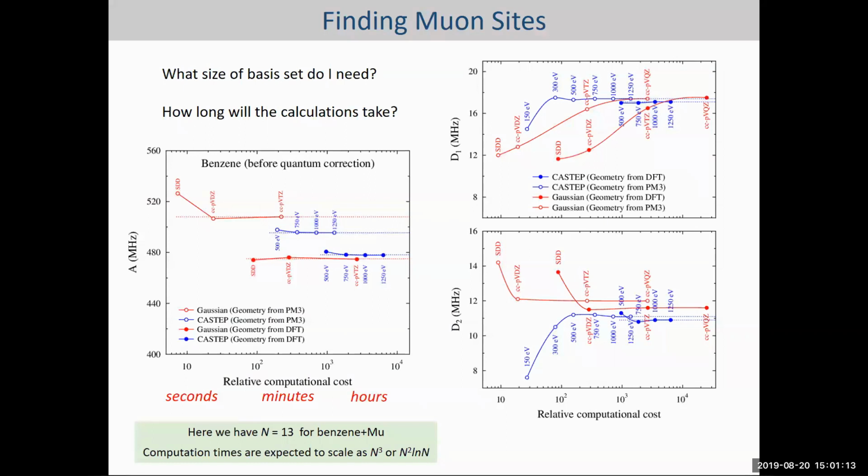Well, to answer these sort of questions, you have to look at convergence tests and see when you converge on the parameters that you're trying to establish. Now, for plane wave type codes like CASTEP, it's relatively straightforward. You just enter a cutoff energy, and you get fairly rapid convergence on your final value. And then you can step back and decide where to place your calculations.